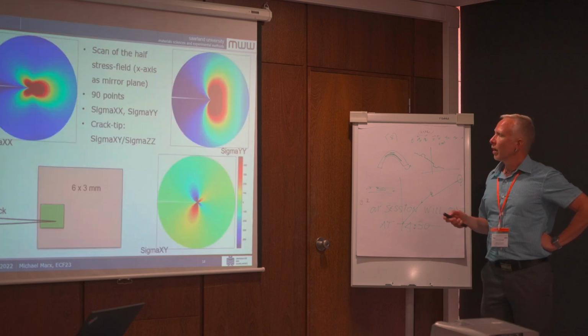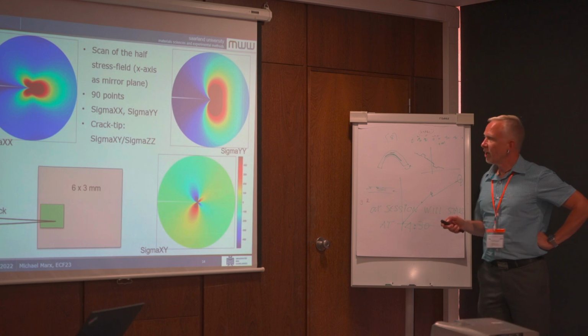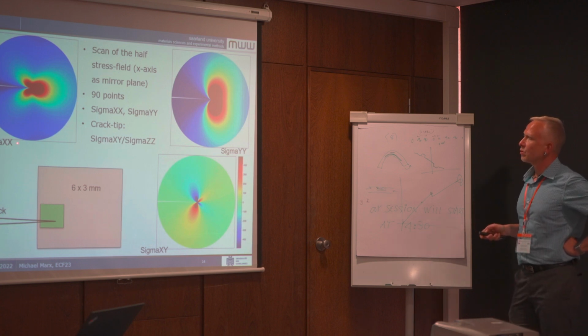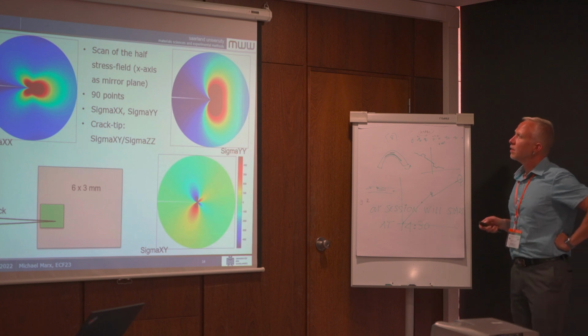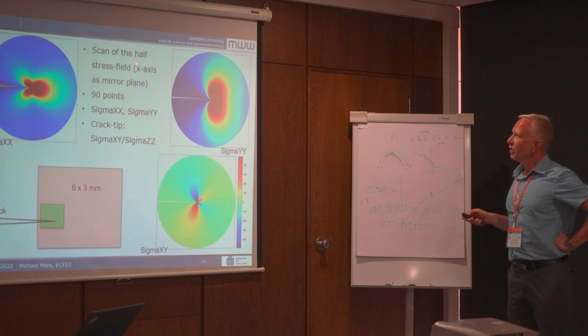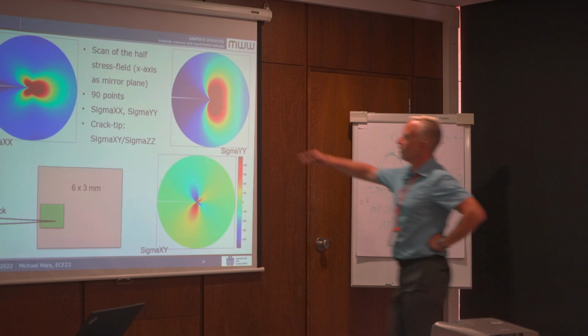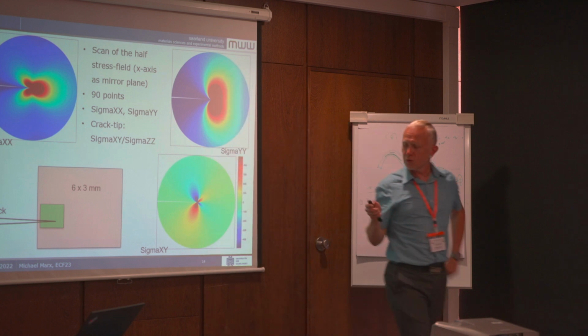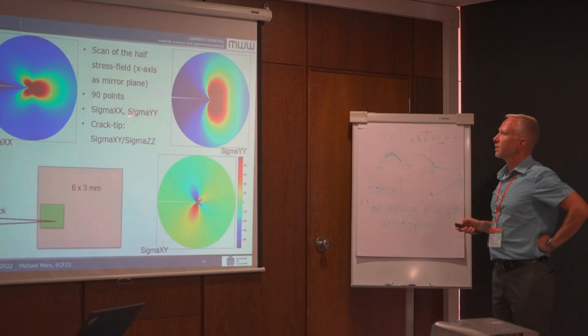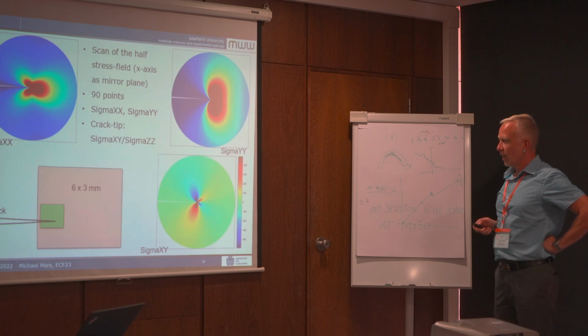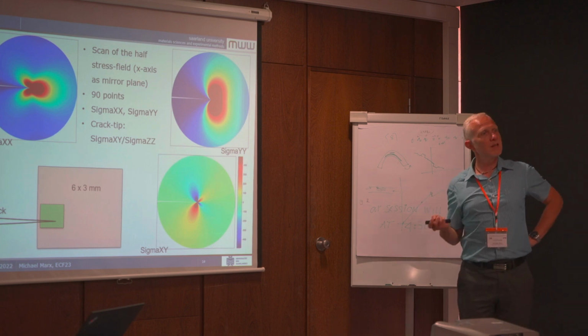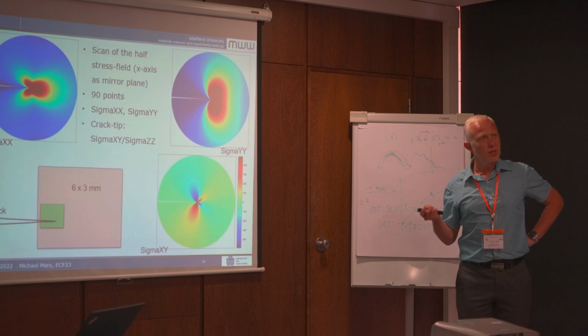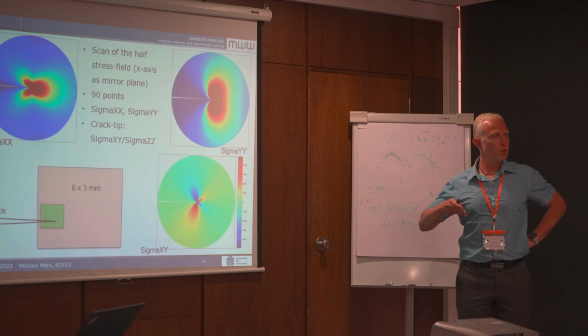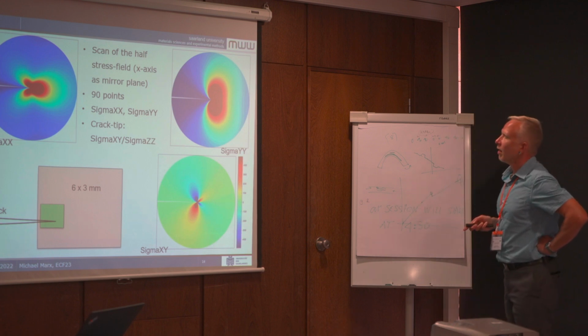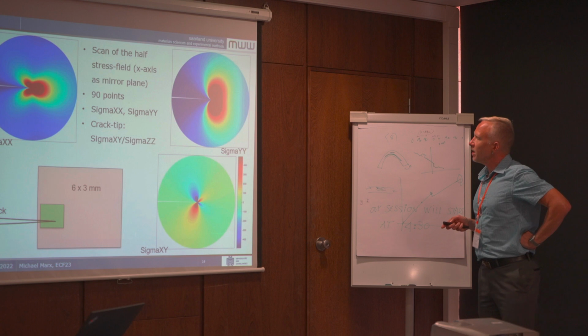And we also made some calculations. How should it look? The stresses, sigma xx, sigma yy. This is what you typically see. And we measured only a half field, maybe only the upper half, and we then used the x-axis as a mirror plane, and therefore our results are symmetrical. This is not what we measured. It's just because of time reasons we were only able to measure the half plane or the half space of the specimen.